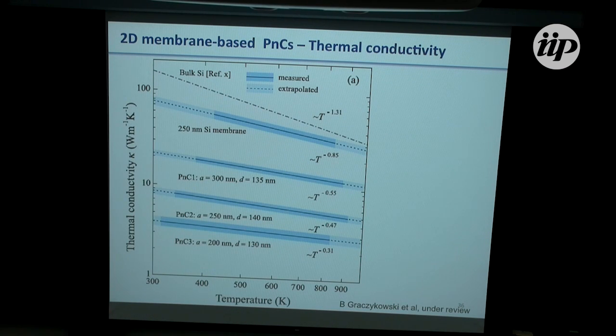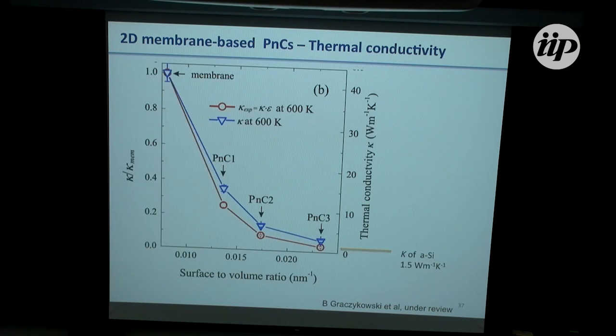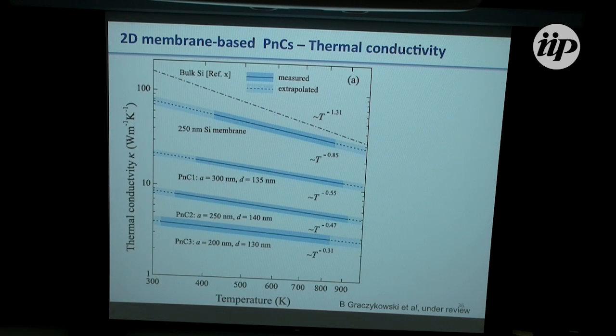Okay, for completion, just the thermal conductivity versus temperature for the various geometries, but it's more illustrative to see the variation of the thermal conductivity compared to the membrane. So this is thermal conductivity of the phononic crystal compared to the membrane, which is 1 here. And here is the surface to volume ratio. And what you see is that depending on the surface to volume ratio, you have a variation of the thermal conductivity, which means that no matter how they are distributed, if you keep the surface to volume ratio, you can dial up a thermal conductivity.